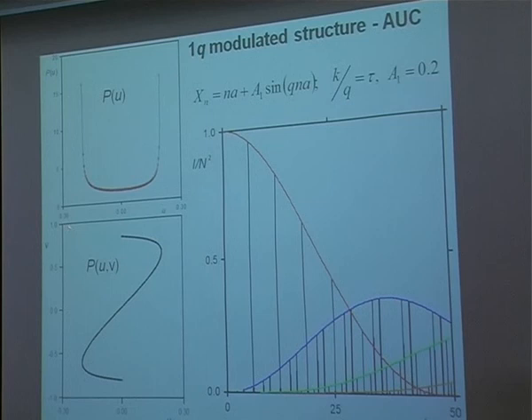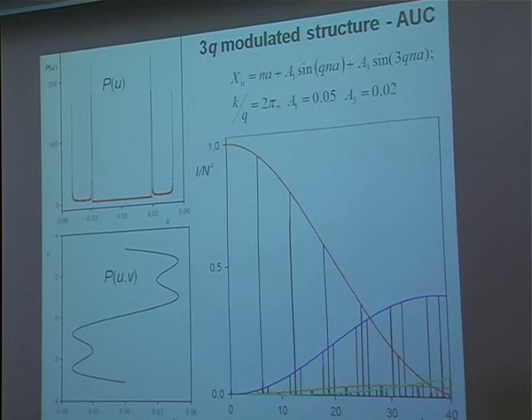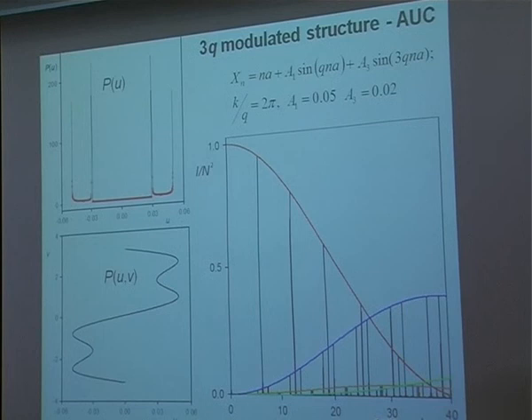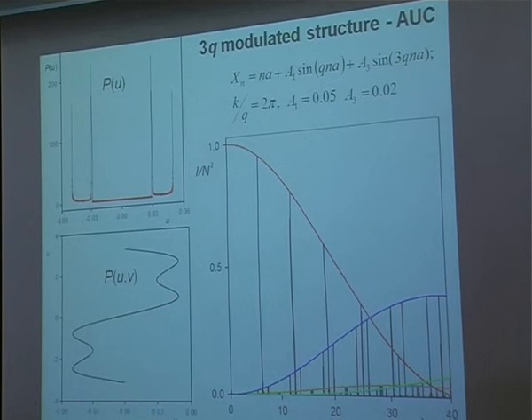You Fourier transform the average unit cell which looks like that. If you complicate the structure — for example a 3Q structure — you have a Q component and 3Q components. The average looks more complicated in the u and v parameters; the line is a composition of two arcsine curves. But if you perform the Fourier transform of this line, you still get the main reflections, then the first satellite, the second satellite, and so on. Nothing is left out — each peak is calculated correctly.